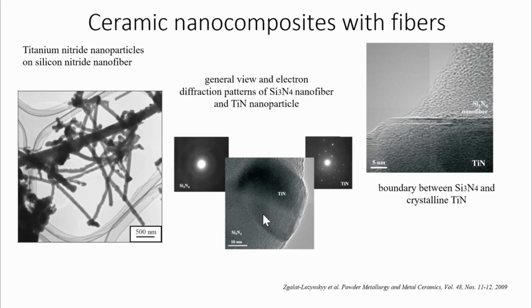According to transmission electron microscopy, fine titanium nitride particles formed during chemical synthesis over the silicon nitride nanofibers. The diameter of the silicon nitride nanofibers was below 100 nanometers, as you can see, and the titanium nitride nanoparticles, which were synthesized on the surface of the silicon nitride nanofiber, were around 20 nanometers.